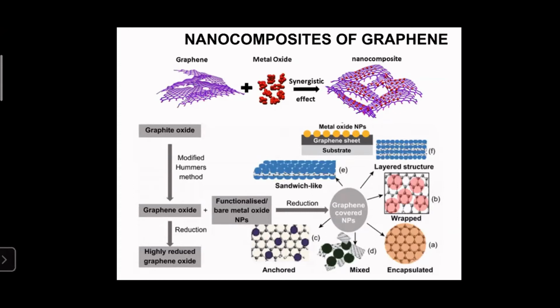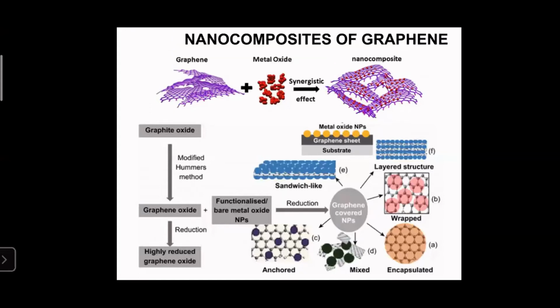But if we use graphene sheets prepared by other methods, we get a perfectly aromatic conjugated network with no defects or functionalities on the sheets, and the electron mobility is very high, but not all metal oxides can form strong composites with this pristine graphene. Some metal oxides such as Fe2O3 form stable nanocomposites with pristine graphene, but in other cases, such as with titanium dioxide, the composite is not so stable. Some of the metal oxides leach out easily.